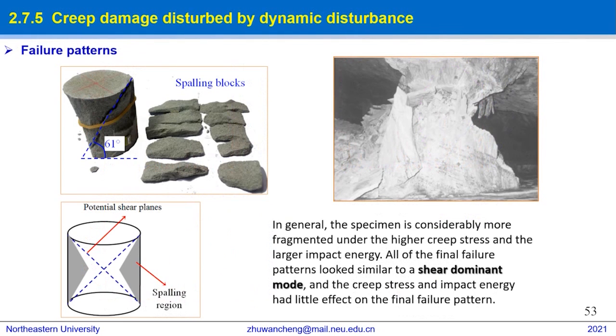This slide shows the failure patterns of rock specimens after the creep impact experiments with different creep stresses and impact energies. In general, the specimen is considerably more fragmented under the higher creep stress and the larger impact energy. All of the final failure patterns looked similar to a shear dominant mode, and the creep stress and impact energy had little effect on the final failure pattern.